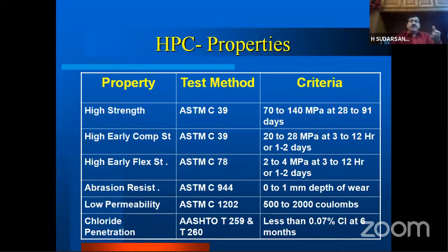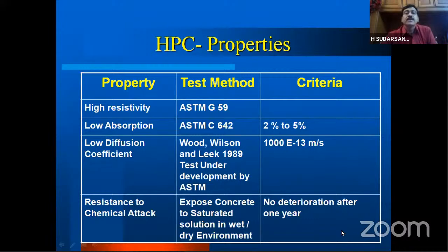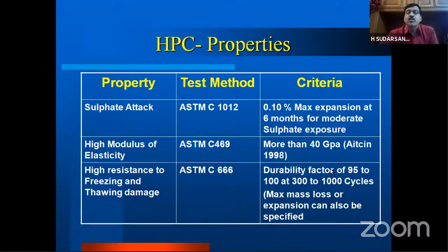Similarly, I have high early flexural strength, abrasion resistance, low permeability. As per chloride ion permeability test, it should be 500 to 2000 coulombs. So chloride ion penetration should be less than 0.07%. So high resistivity, low absorption, for all this I have prescribed the codal limits. I have just listed the codal limits. You can just go through them.